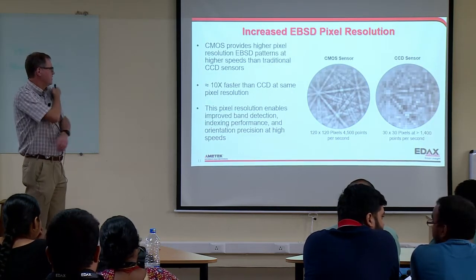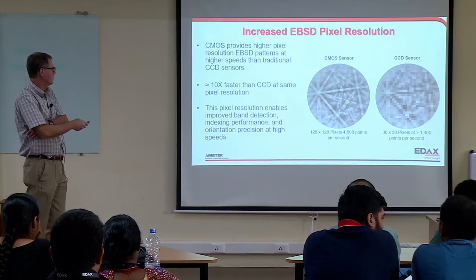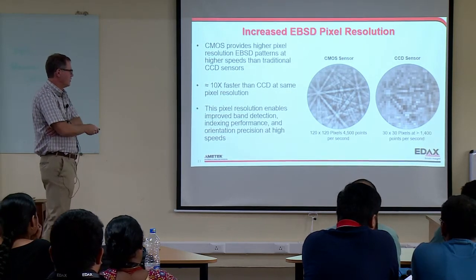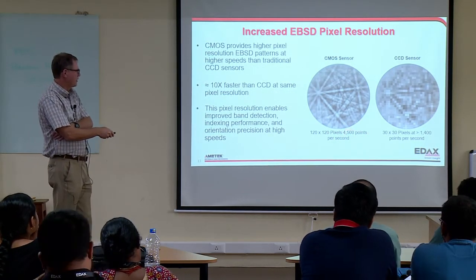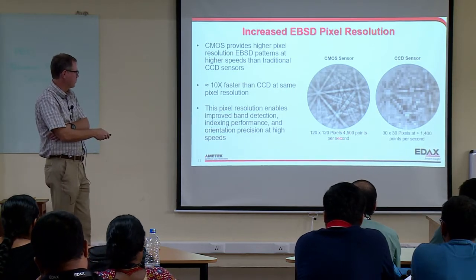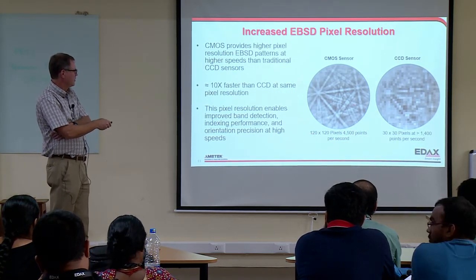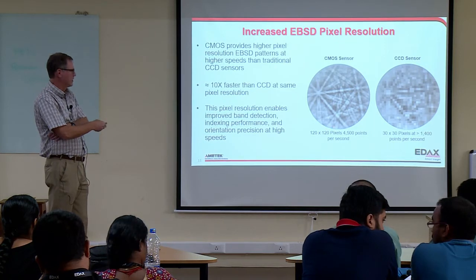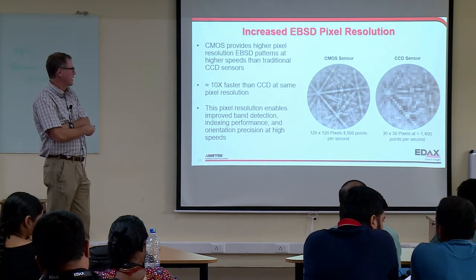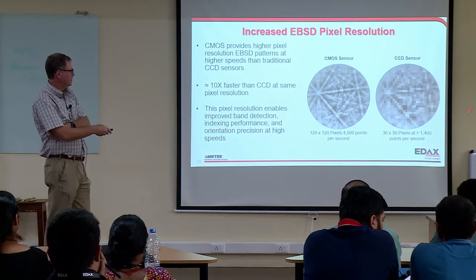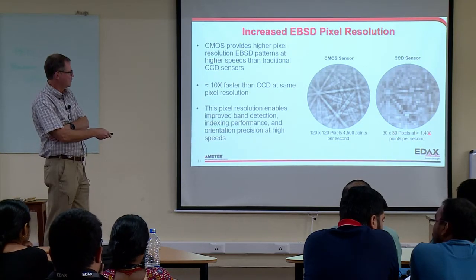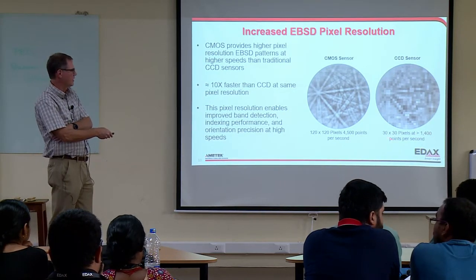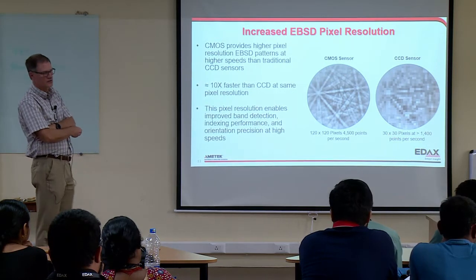So the nice thing about CMOS then is we can go really fast at much higher resolution. For example, here at 4,500 points per second, which is our maximum speed at 120 by 120 pixels, we get a beautiful pattern like this. Once again, this is our test sample of nickel. Here it is on a CCD sensor. The fastest we could get to is about 1,400 points per second, and that's at 30 by 30 pixels, so much less pixel resolution.